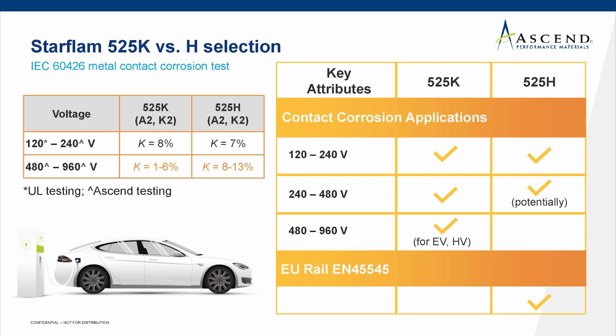And so we like to designate the K grade for higher voltage applications, but the H grade, as we showed you before, with the RTI values being much higher, there's an advantage for applications that require that, as well as the H grade exhibits lower smoke density that satisfies the European rail requirements. And it can satisfy interior requirements of R22 HL3, as well as the exterior.